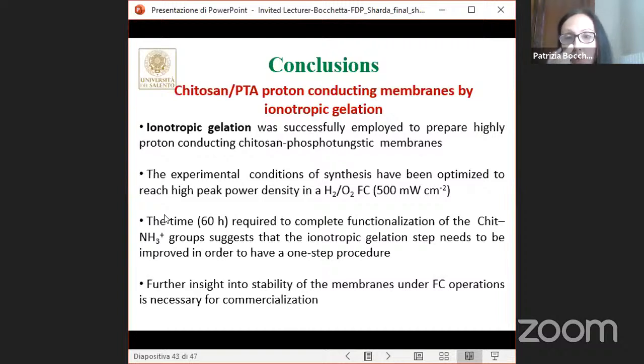So we are at the conclusion. What we can say is that ionotropic gelation was successfully employed to prepare high proton conductivity chitosan phosphotungstic acid membranes. The experimental conditions for the synthesis have been optimized to reach high peak power density in a hydrogen-oxygen fuel cell, about 500 milliwatt per square centimeter. The time of 60 hours is identified as the time required to complete functionalization of the chitosan amine groups. And this suggests also that the ionotropic gelation step needs to be improved in order to have really a one-step procedure. Further insight into stability of the membranes under fuel cell operation is necessary, of course, for commercialization.